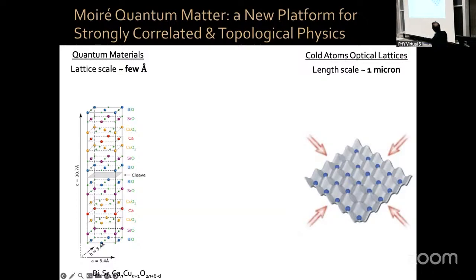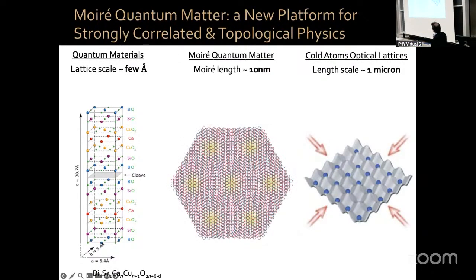Here with the cold atoms, this time the length scale is about a micron, the wavelength of light. Here we have exquisite control over all the parameters of the system. So we can do experiments just in a single platform, in a single lattice. However, because of this high temperature limit, the number of phases of quantum matter that have been observed has been limited so far. And what I want to tell you about today is this new platform, Moiré quantum matter, which is complementary to these two other platforms. It's also complementary in terms of length scales. The Moiré length is of order 10 nanometers, so it's a factor of 100 from either of these other two platforms.